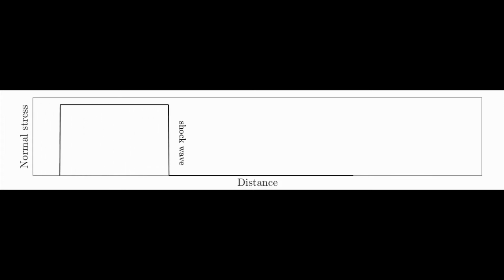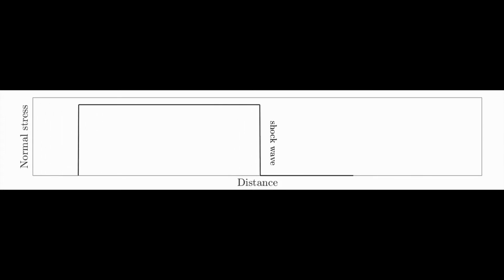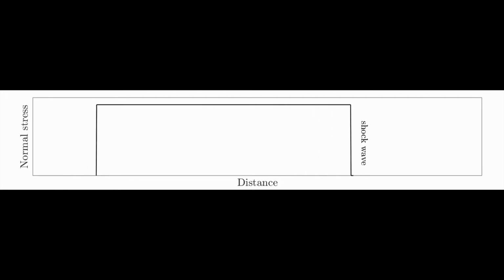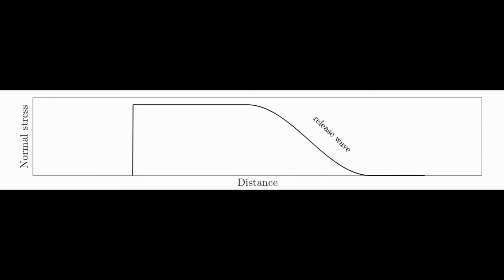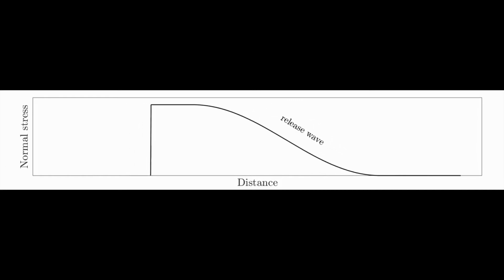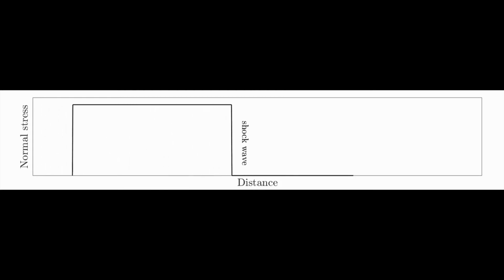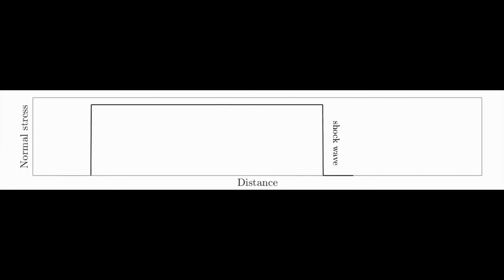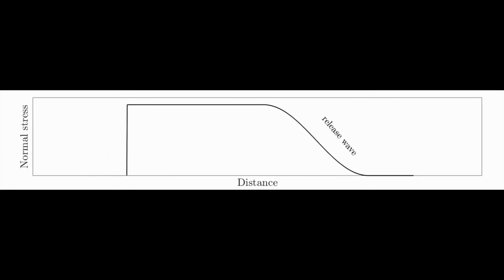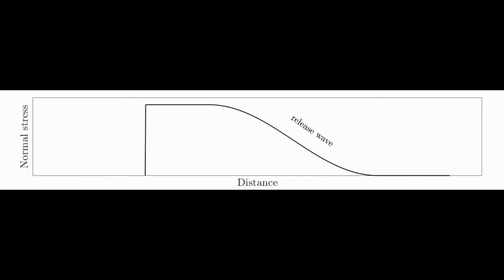To begin, I thought I'd show a simple animation illustrating in a schematic way what the shock release process involves. So we start by rapidly loading the front surface of our sample in order to generate a shock wave, behind which the material is high density, high pressure, high temperature, high velocity, and so on. That shock wave propagates through the sample in a nice self-similar way until it reaches the rear surface, at which point it encounters a free boundary that is completely unable to support the state of high stress engendered by the